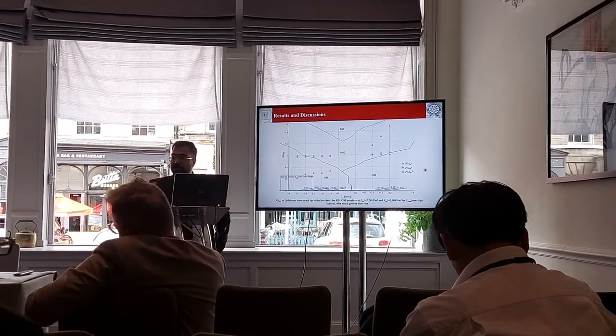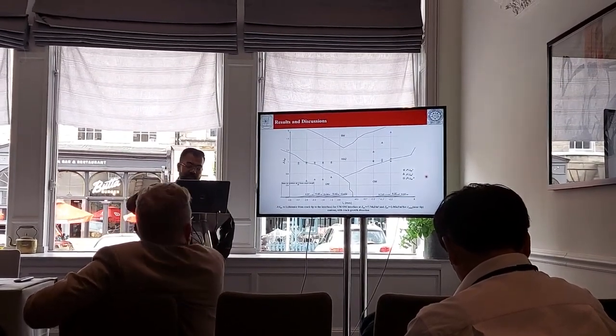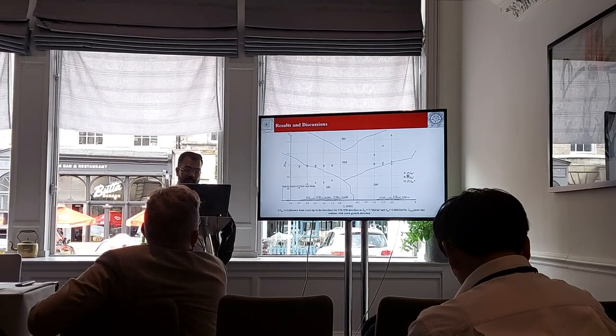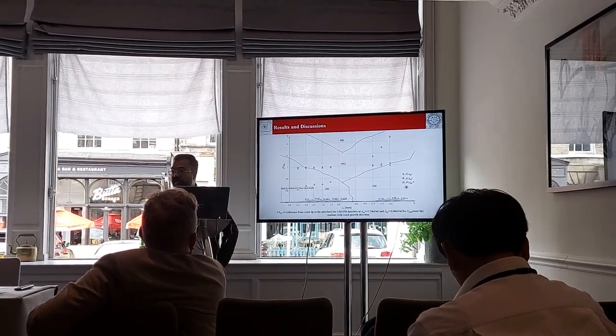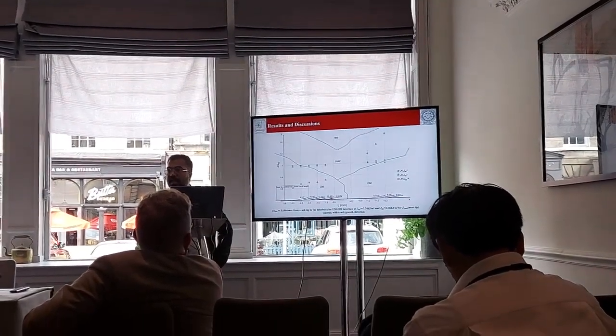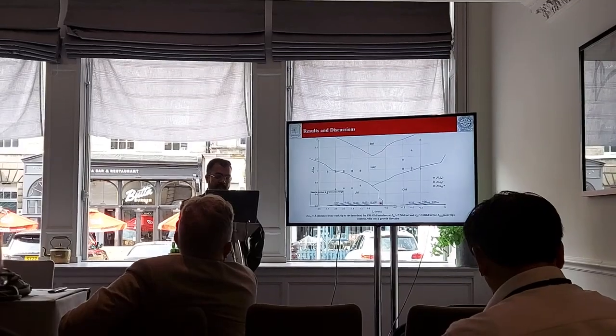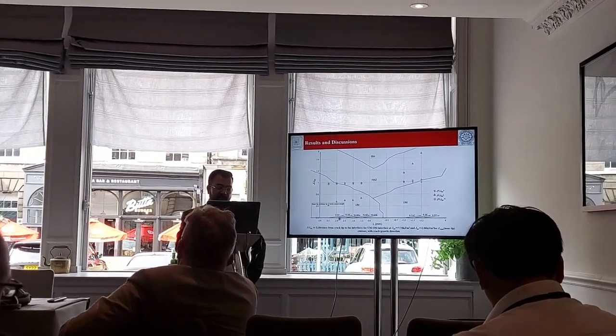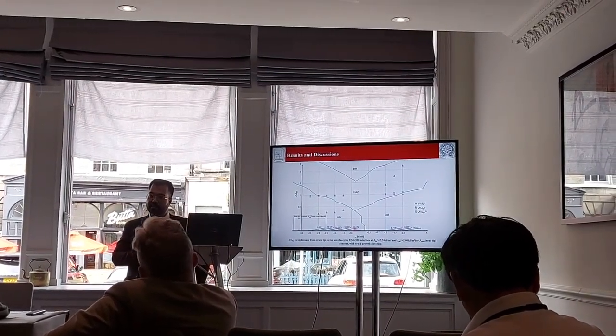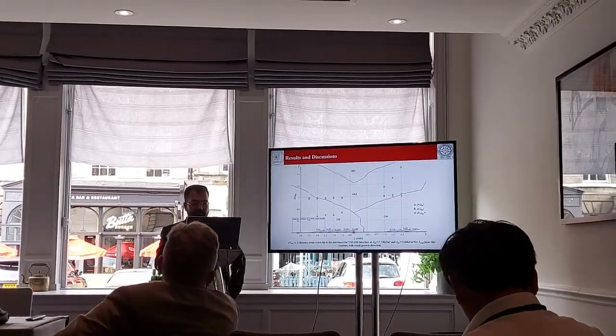And so here on this plot, this is in dimension. So on the x-axis is the real dimension of the specimen. And here you see different components normalized by the J far values. So you have Jx component, Jy component, and J resultant component. And from that J resultant, we have calculated how much deflection would appear as the crack approaches towards this interface. This is not a very simple scenario. It's a complicated scenario, but what you see is that the angle of deflection increases, decreases, increases, decreases. The trend is that it increases as it comes closer to the interface from the very beginning.